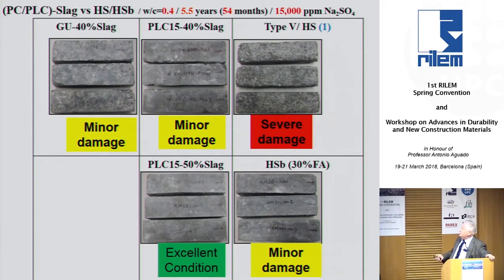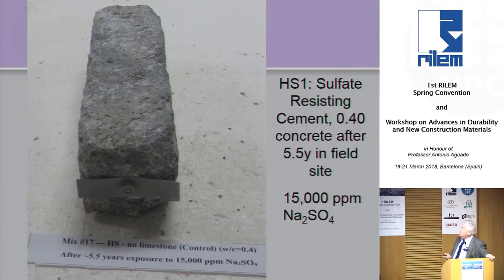If we put enough slag in, 50% slag, which we would normally use with that particular clinker, there is no damage at all. This is a sulfate-resistant cement that's currently allowed in the system. So a low C3A Portland cement that has been used for almost 100 years in Western Canada, and they're severely damaged in this environment. So after 5.5 years, they're severely damaged, but the mixture of even a high C3A cement with sufficient slag is fine. And this is another system with 30% fly ash with a moderate C3A clinker that's also sold in Western Canada for sulfate environments. So we're seeing there's no difference.